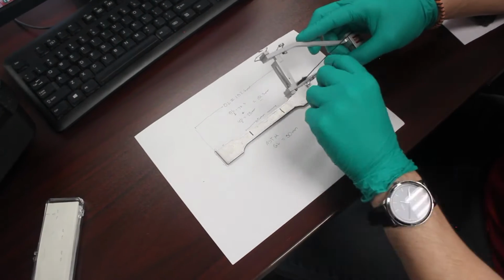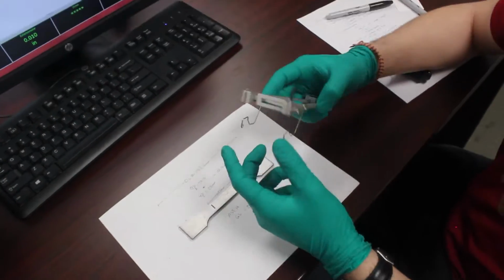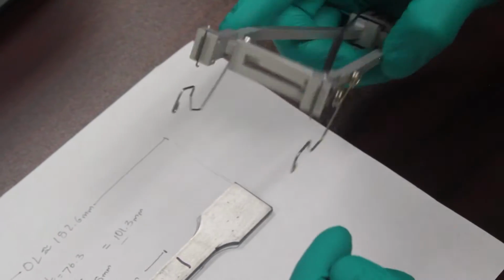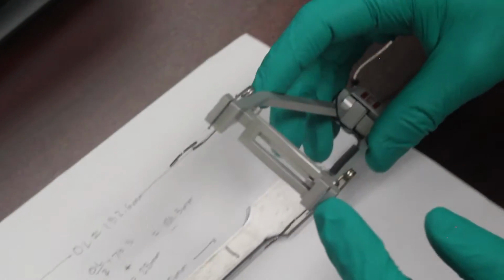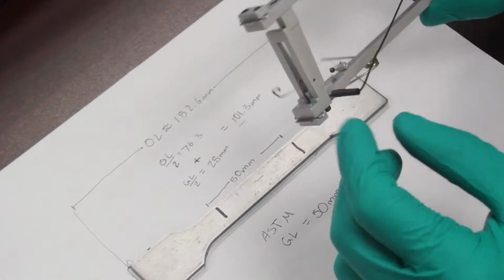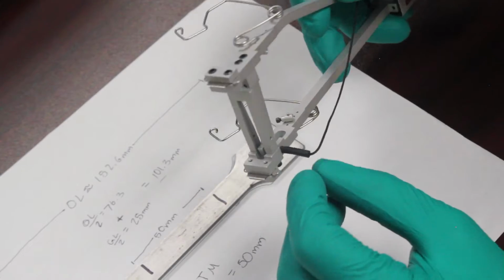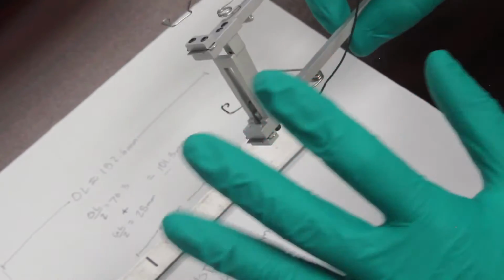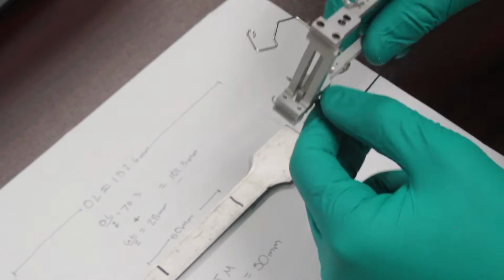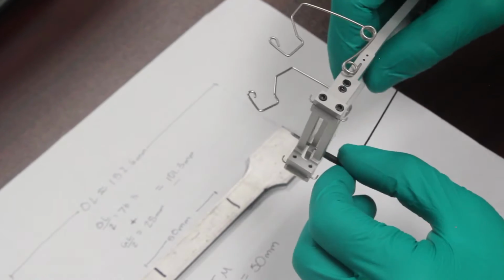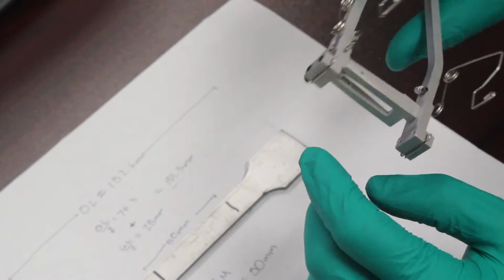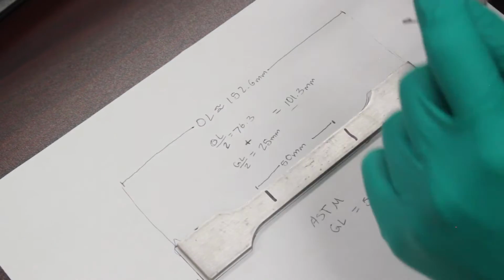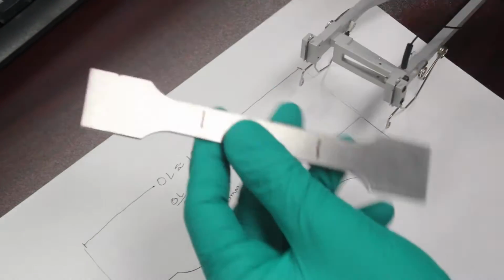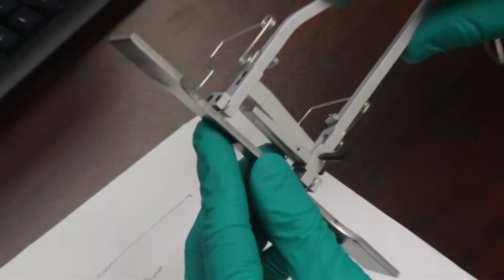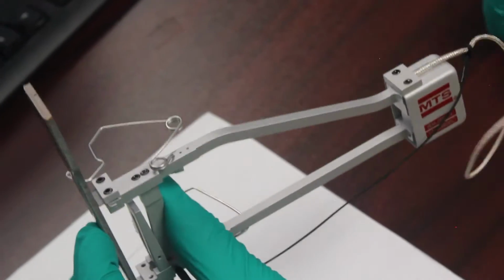Here we're going to attach the extensometer to your tensile sample. Move the retaining clasps out of the way, and these are the knife edges which will line up with the Sharpie marks to indicate the gauge length for your tensile sample. This black pin is inserted to make sure the extensometer stays at 50 millimeters until you're ready for the test. Now, you're going to align the knife edges with the Sharpie marks on your tensile sample. Place the extensometer against your tensile sample and use the metal retaining clasps to hold them together for the time being.